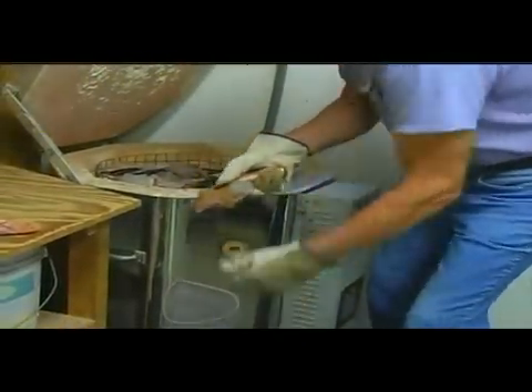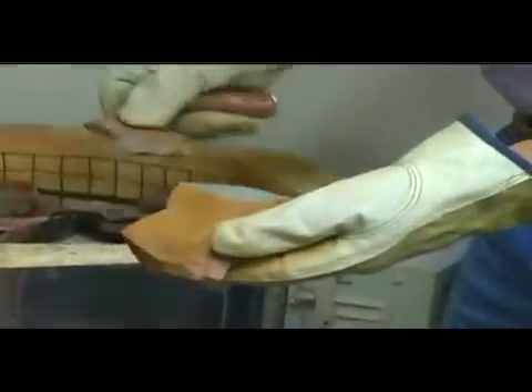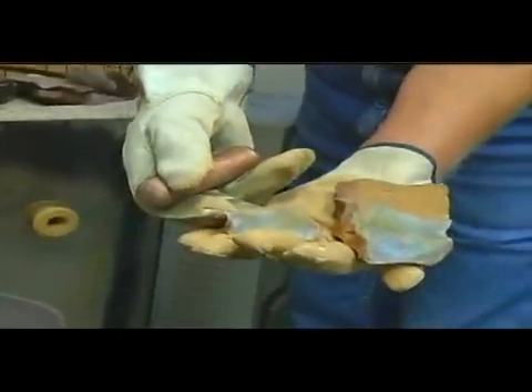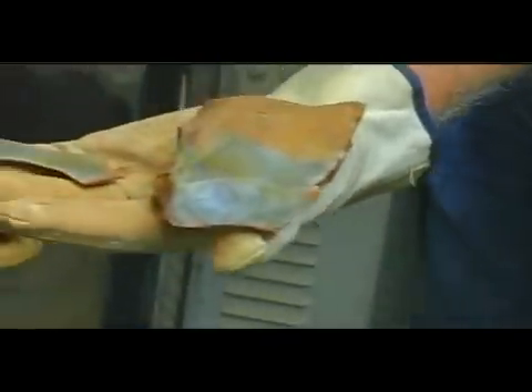Here's a piece that's potlidded. It was out toward the coils, and you can see when the kiln keeps cycling on and off, it finally gives in. A lot of times when you have these, you also get heat cracks inside. We'll check this in a little bit to see if it does. It doesn't seem to — you can see it isn't smooth, silky looking. That's some of the really fine knapping flint.